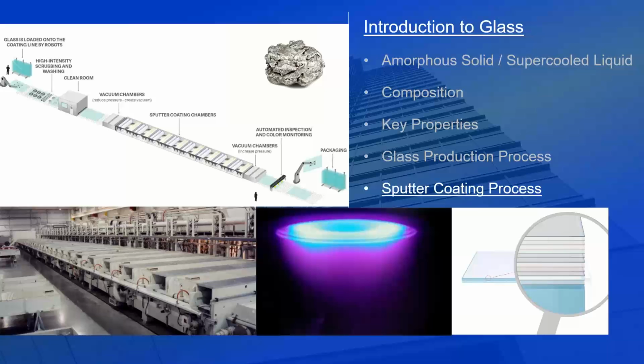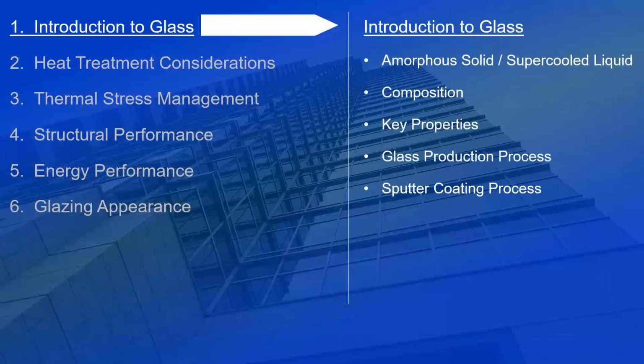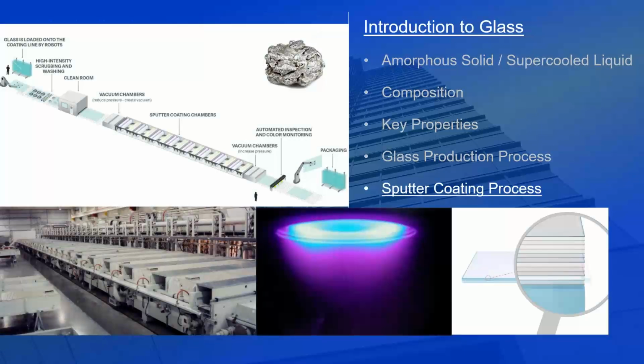Some Low-E coatings may have 5, some may have 7, some 12, some 25 or more different layers of metal in their Low-E coating stack. I'll go back real quick. That nugget there in the top middle, that's representing silver. Silver is the workhorse of Low-E coatings. There's single silver, double silver, triple silver Low-E coatings. And in the residential industry, if you hear terms such as a double Low-E or a triple Low-E, oftentimes they're referring instead to how many layers of silver are in the Low-E coating stack.